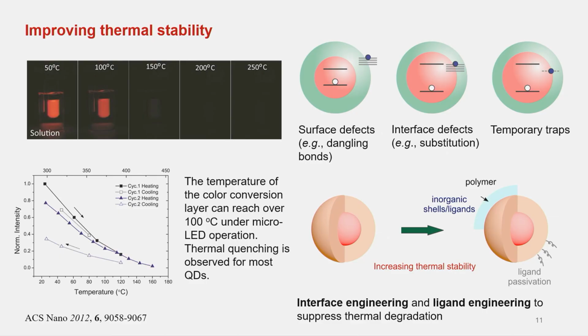For example, if it's more on specific surface defects, we can find ligands to passivate those defects. Some people argue that it's actually degradation of the organic ligands, then we can change the organic ligand into an inorganic ligand that will sustain under 100 degrees, for example.